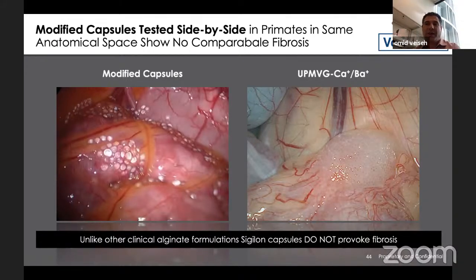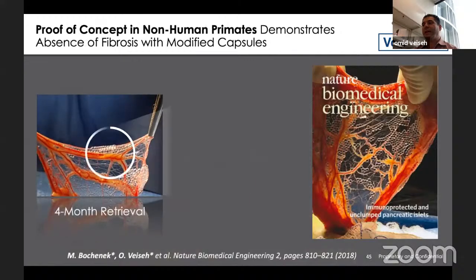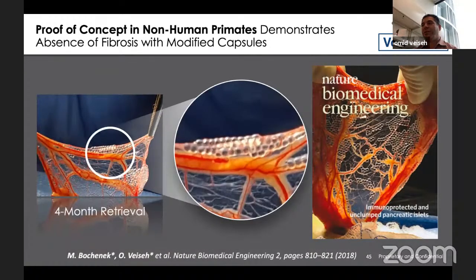So this helped provide a link between where the field was in terms of stuff that wasn't working in humans. Now we show that those also don't work well in non-human primates, but with the modification, we're able to see great results in non-human primates with our formulation. And this actually, in non-human primates, results in encapsulated cells remaining viable. And we also identified perhaps a preferred implant site, which is the bursa omentalis.